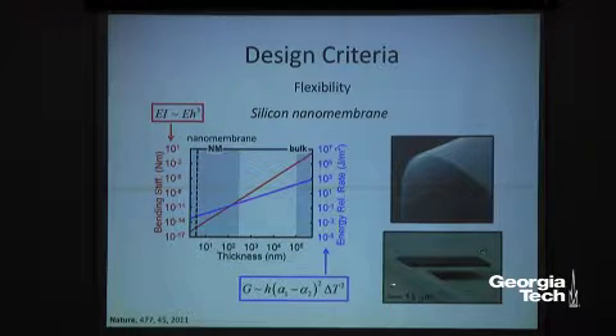Now, this device is made of silicon nanomembrane on this photoresist pattern. So it's cantilever. We didn't use any adhesive. It's purely based on van-der-Waals interaction between two materials. But without that adhesive, you have negligible crack propagation in terms of energy. So now we can have this structure. So in the same way, you can build multiple patterns or even more complicated 3D structures based on this nanomembrane. So that's the beauty of thin material.